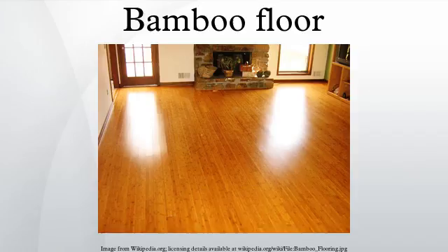The panels are then heat-pressed to cure the adhesive. The cured boards are then planed, sanded, and milled. Finally, an ultraviolet curing lacquer is applied to the boards. Manufactured bamboo floors are typically made available in planks with either vertical or horizontal grain orientation. In vertical bamboo floors, the component pieces are stood vertically on their narrowest edge and then press-laminated side to side. The effect is a lined, almost uniform look to the surface of the finished floor plank.